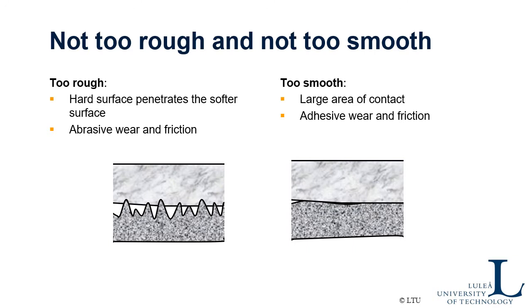If you make it too smooth, on the other hand, you create a large area of contact and the contact pressure is much lower, so you may not have any plastic deformation and don't damage the surface that way. But since you create a big contact spot with adhesive forces, that may create a lot of friction and eventually also wear, because atoms on one surface may not recognize they are not on the same surface as the other — especially if both surfaces are made of the same material. In both cases, this gives us motivation to understand roughness better.